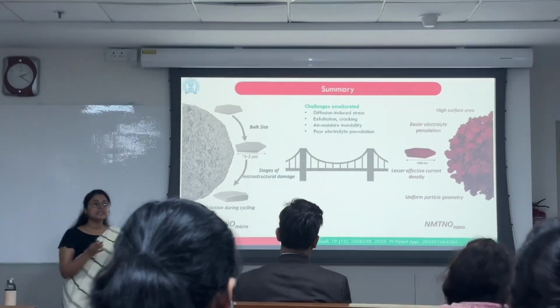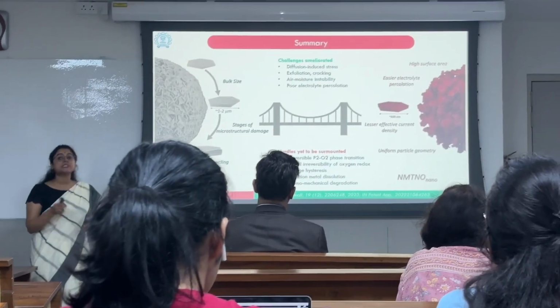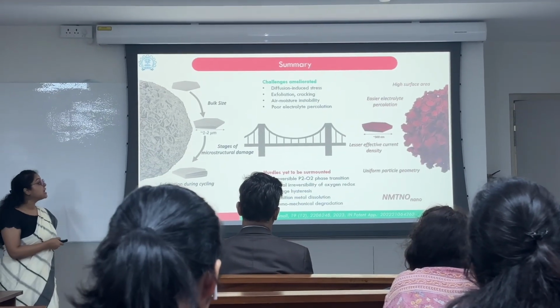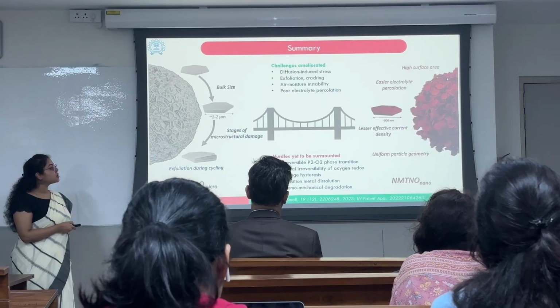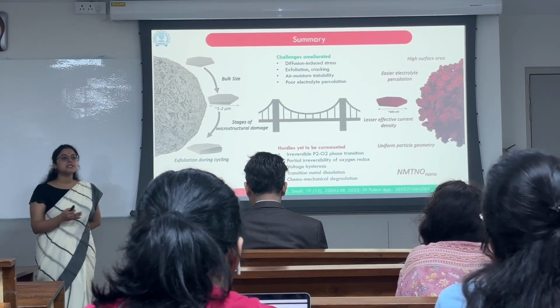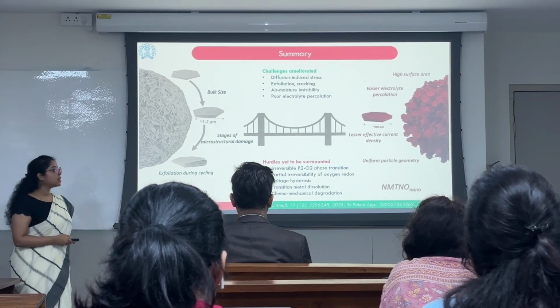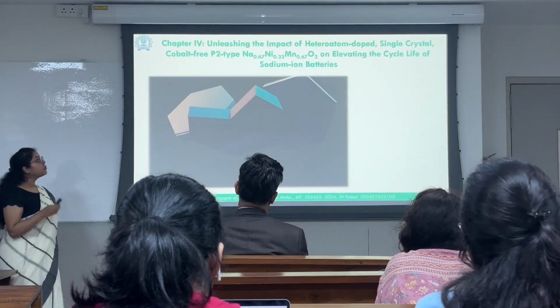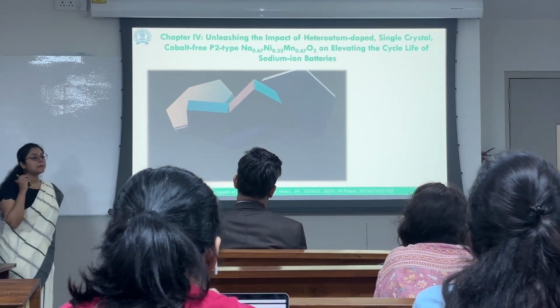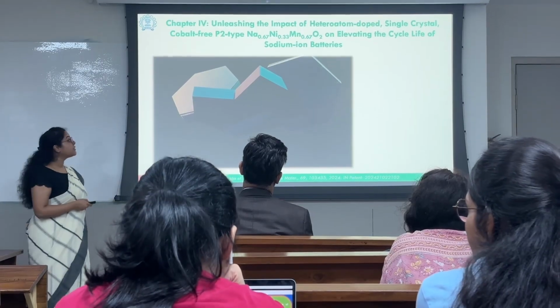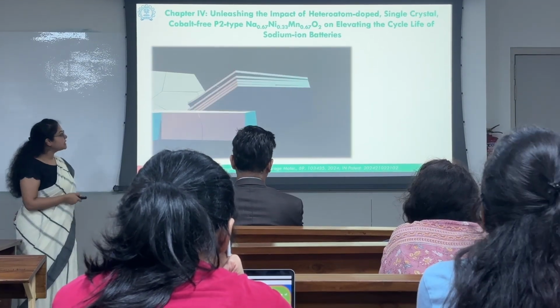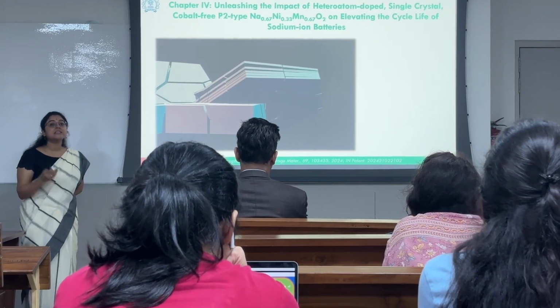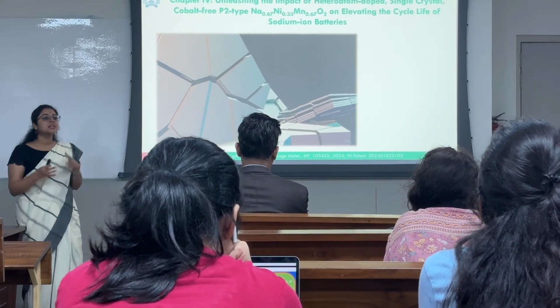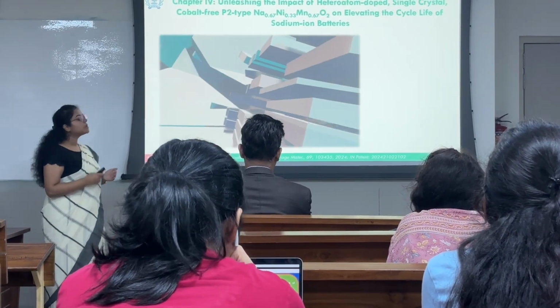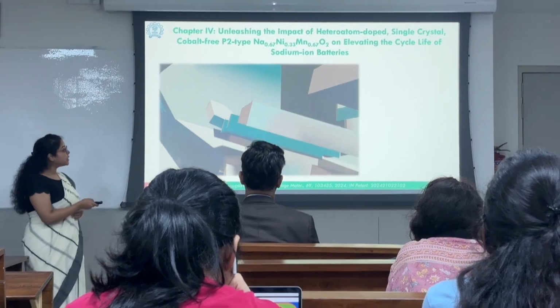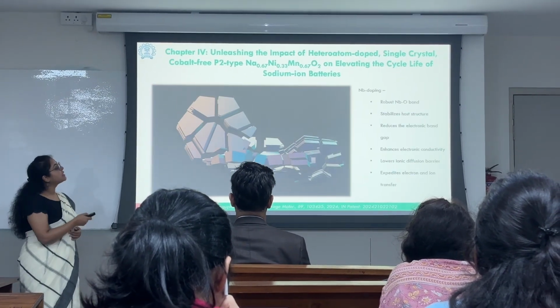However, there is still attention needed for the problems such as the irreversible P2-O2 phase transition, the partial irreversibility of oxygen redox, the voltage hysteresis, transition metal dissolution, and chemomechanical degradation. Hence, in the next chapter, we found out the impact of heteroatom doping in elevating the cycle life. So we have seen that exfoliation and cracking is a major cause. However, the reason behind this is the irreversible P2-O2 phase transition, which we dealt with by doping niobium.